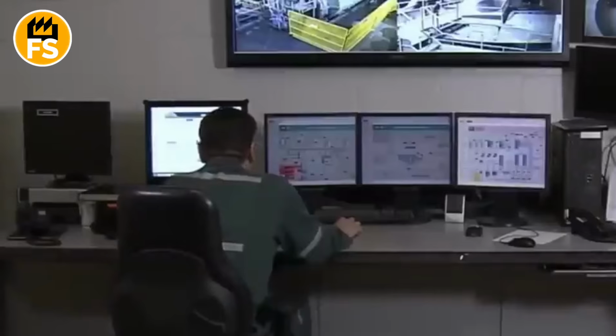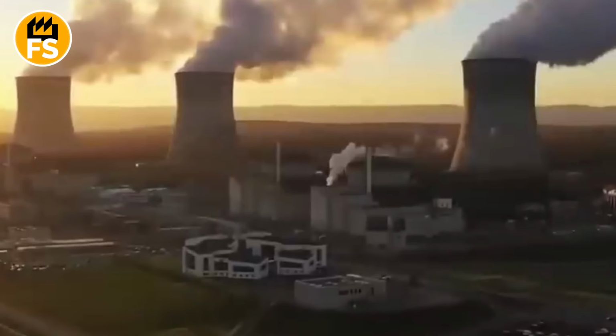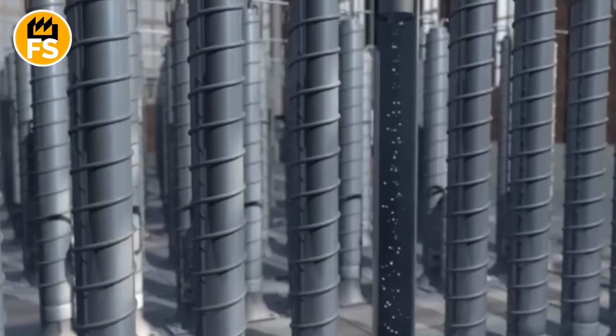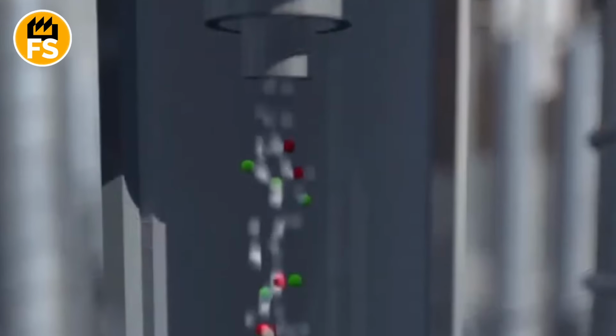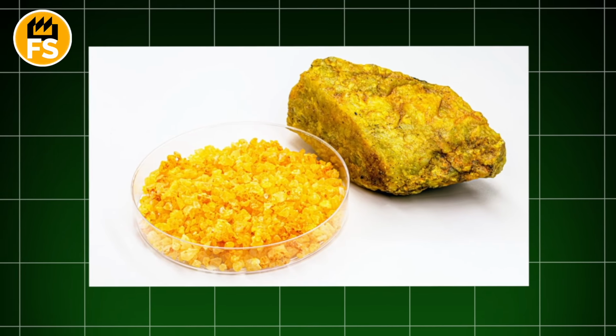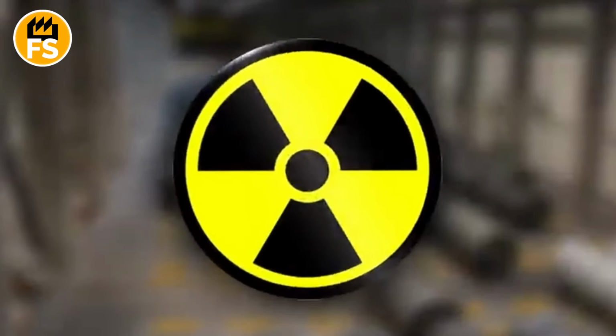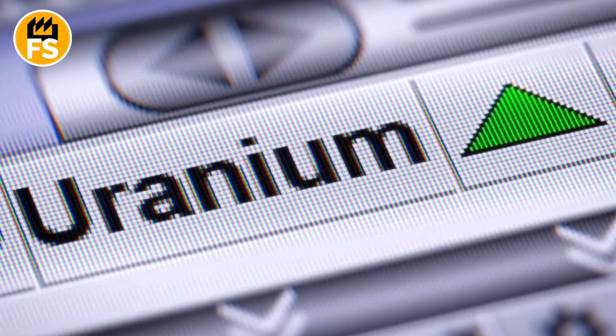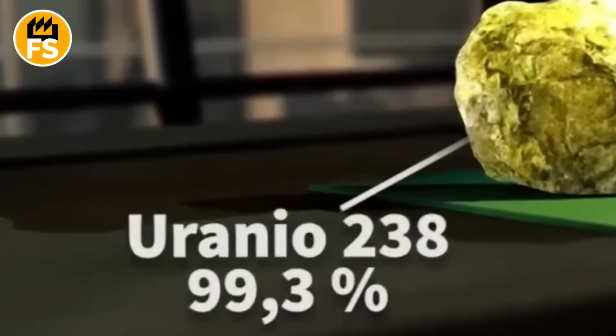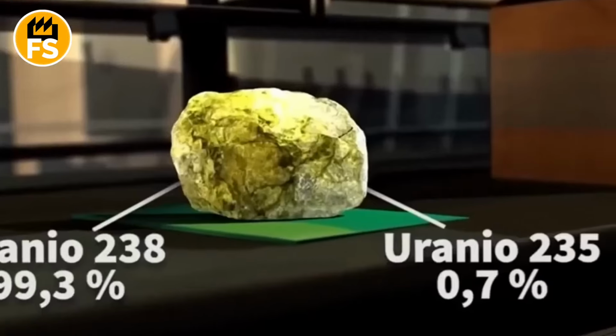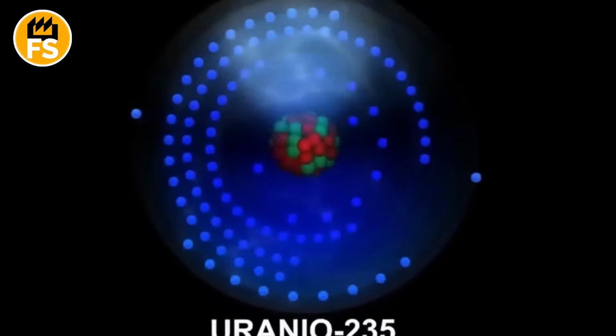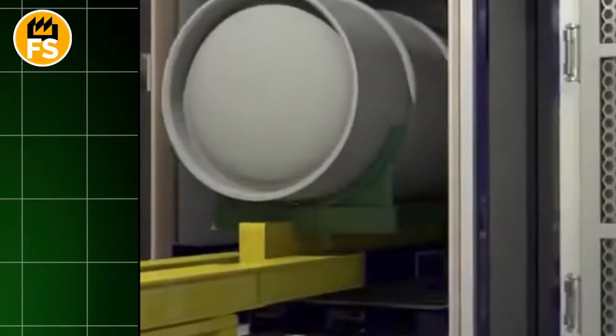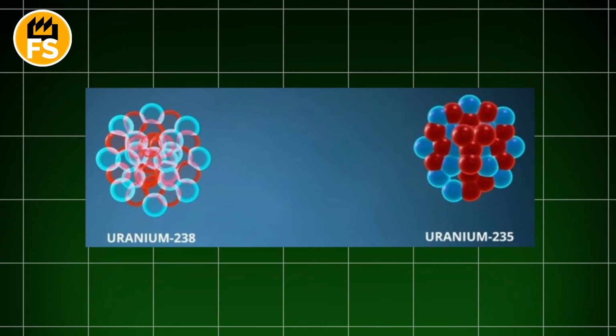The next step is purification to an absolute, almost unearthly purity. The yellow cake is sent to a special plant, where it is dissolved and, with the help of complex chemical processes, such as solvent extraction, all impurities are removed from it. The goal is to obtain perfectly pure uranium dioxide. But here the main problem arises, which is at the heart of all nuclear energy. In this perfectly pure uranium, 99.3% is the stable, lazy isotope uranium-238, which cannot sustain a chain reaction. And only 0.7% is the energetic, unstable isotope uranium-235, which is our fuel. They are chemical twins, and it is impossible to separate them by chemistry.